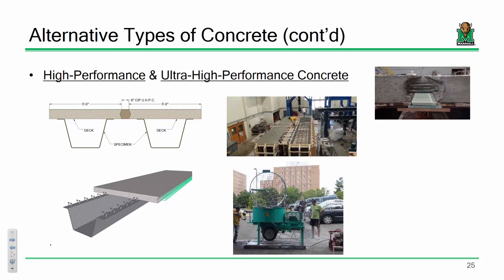Yes. Do you think the lifespan of these is still going to be approximately 75 years, or is it going to be greater? We did fatigue testing on these where we took the fatigue truck under this large capacity actuator and literally did this for enough cycles to simulate 75 years. It was as strong at the very beginning as it was at the end. So, to answer your question, we did that. It took months, but we did it.